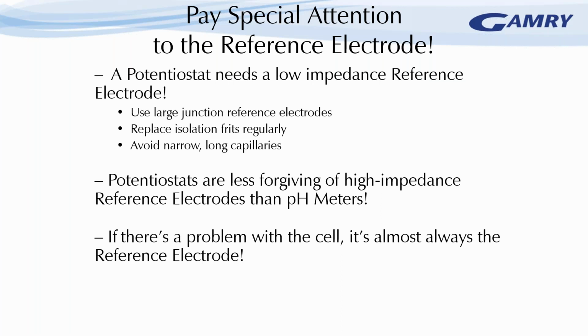as in the case of a potentiostat, it needs to have a low resistance, or low impedance, as it's called. That can be achieved by having a large junction at the tip of the reference electrode, using highly porous glass frits. Because they have very fine capillaries, these can sometimes be blocked, and so regular replacement of these isolation frits can help to improve the impedance measurement of the electrode.